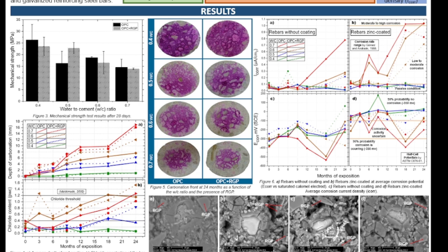For carbonation and chlorides in figure 4, we compare the 24-month exposure period against the depth of carbonation in part A, depth of carbonation in millimeters, and chloride penetration in part B. In this case, we have the chloride threshold, and the corresponding measurements were taken every 3 months, showing that the higher the water cement ratio, the greater the carbonation and chloride ingress. However, with RGP in ratios of 0.4 and 0.5, chloride ion and carbon dioxide penetration decreased significantly due to the densification of the matrix.